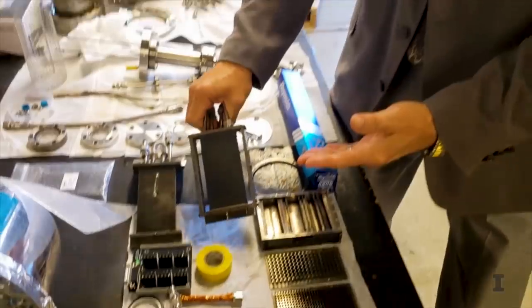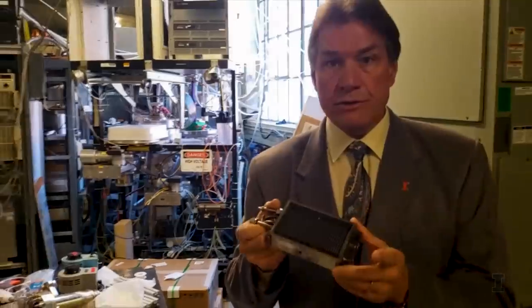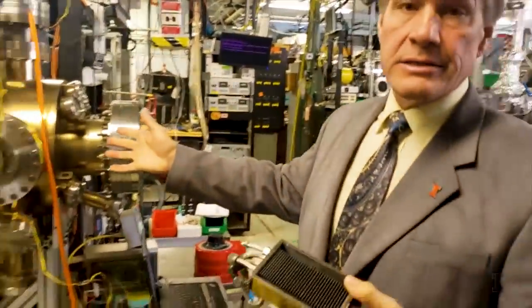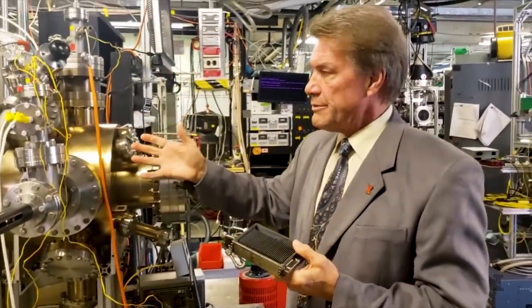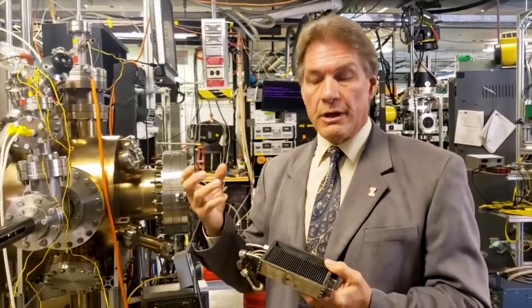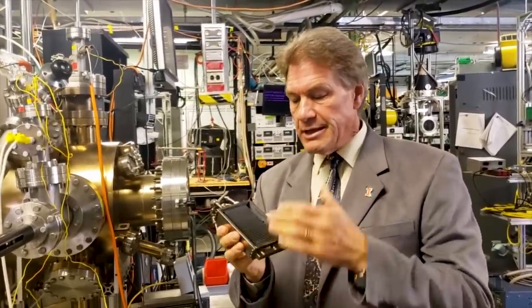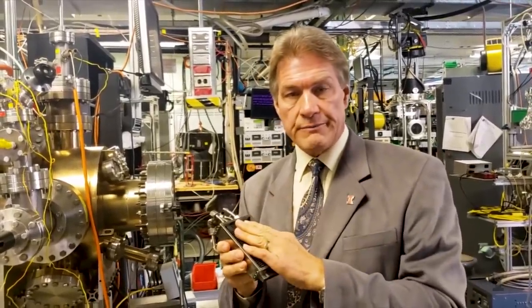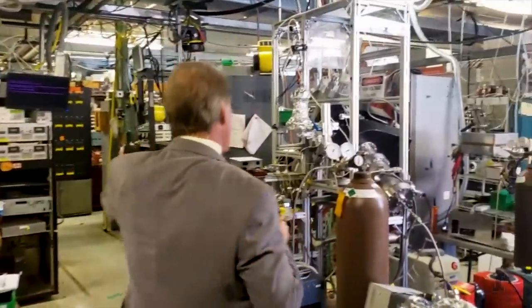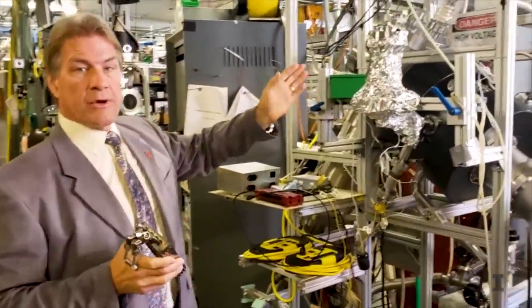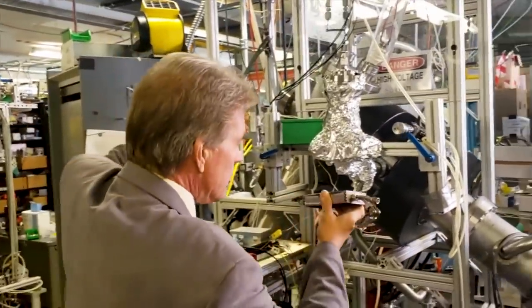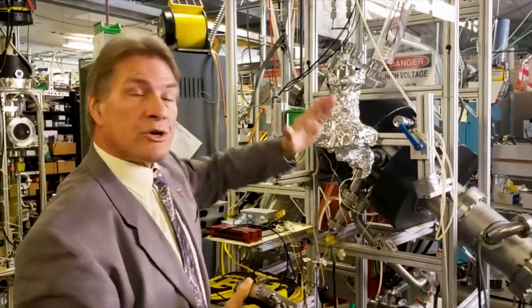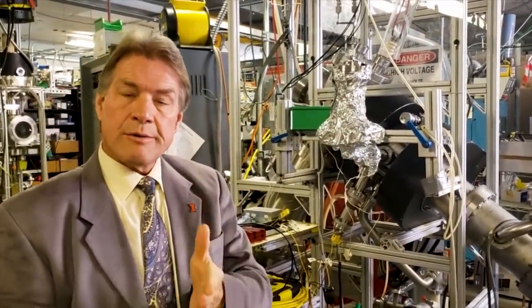This is one of the structures I showed you, and we have many more too. I'm here at the Center for Plasma Material Interactions, my laboratory, where we actually test this type of device. We do this in two different machines. One of them is MCATS, which is designed to allow high temperature lithium to come in a very good vacuum system, which will tell us if things wet, if the lithium is actually compatible with this material and if it flows across it. And then, just this way, we have our high heat flux facility. We call it SLIDE, and it has this structure in the middle by the magnetic fields with an electron beam that goes in a sheet and can simulate the plasma actually hitting the device at high heat fluxes.